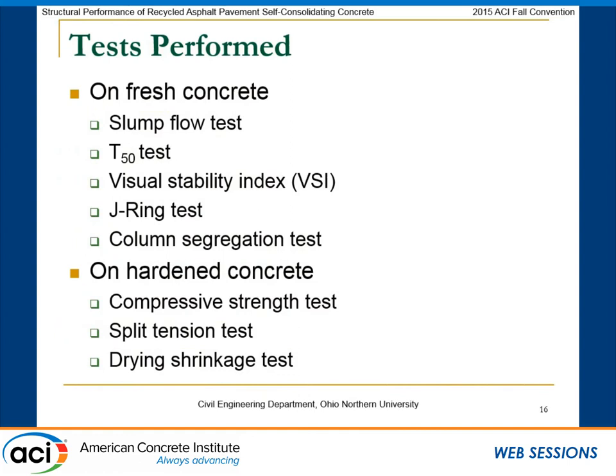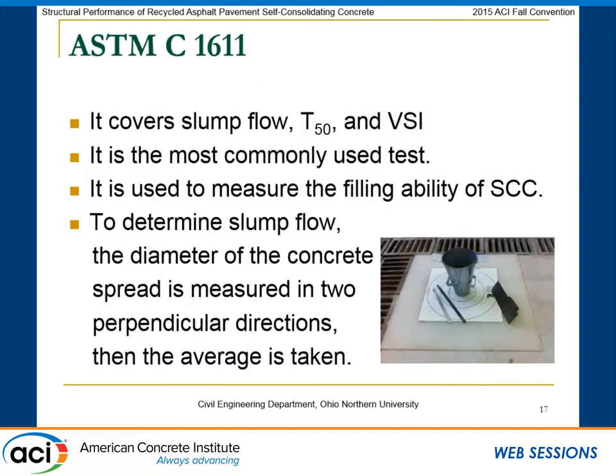So we did the testing, as I said, on the fresh state of the concrete and also the hardened state, and also we looked at the shrinkage as a measure for the durability of the concrete that was produced. So the common tests which are done on SCC, we did the slump flow test, T50, VSI, J-ring test, column segregation test, which is really hard to do. It's a very physical test. And then for hardened concrete, we did the compressive strength test and the common split tension test and the drying shrinkage test as a measure for durability.